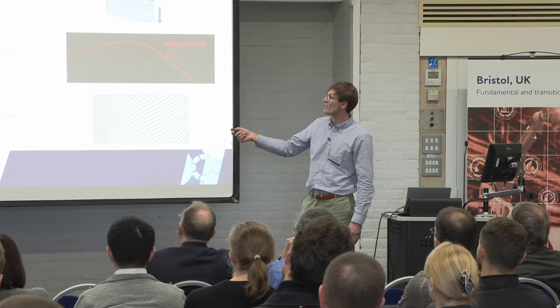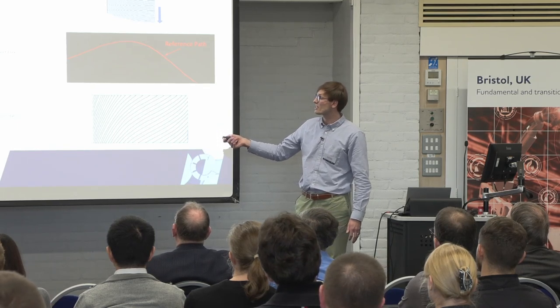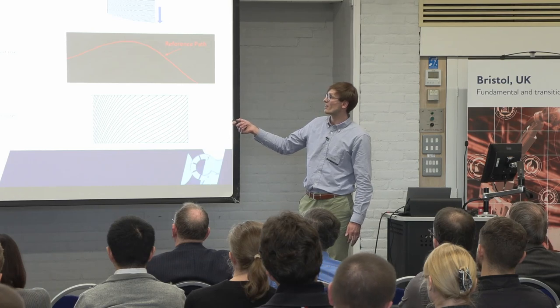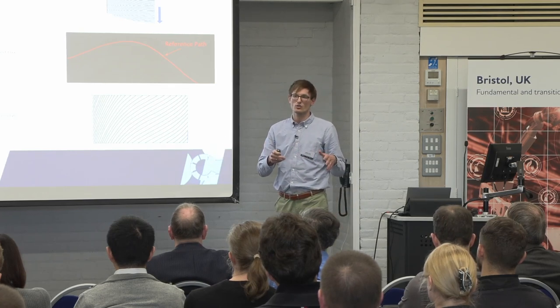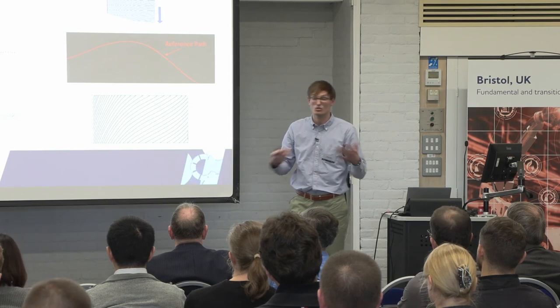You get fiber wrinkling on the inside radius and fiber liftoff on the outside. The second disadvantage of this is because you effectively across the tow have different steering radii. The outside has a larger steering radius than the inside. It's very, very hard to tessellate individual tows. And so you get gaps and overlaps that can, of course, lead then to material failure in these resin pockets.